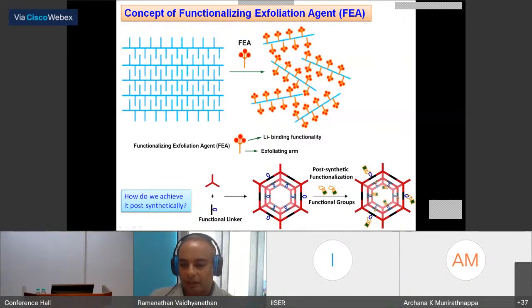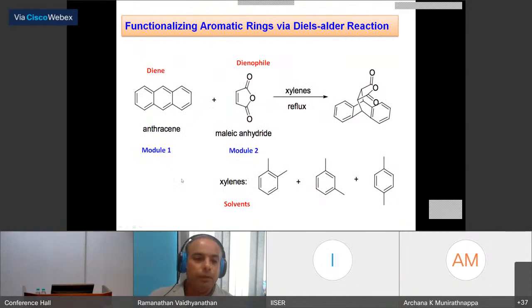And you can see that it has a lot of similarity to this post-synthetic approach, which I explained in the previous slide. Now, what is the chemistry? The beauty of the chemistry is shown in this particular aspect. You can take a diene, which is the anthracene in this case, which can be called module one, and you can pre-coat this diene into the COF. And then you can have a dienophile, which in this case is maleic anhydride, which I can call module two. And I'm going to introduce this after the COF forms so that I create what is a 4+2 addition reaction, and then I get an adduct, which has a functional group which is very favorable for binding with incoming guests.